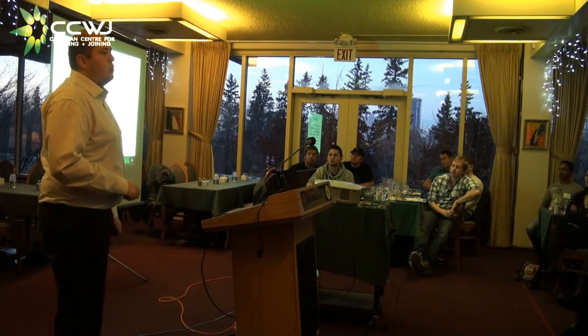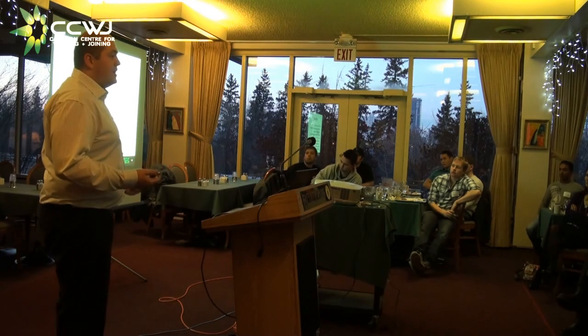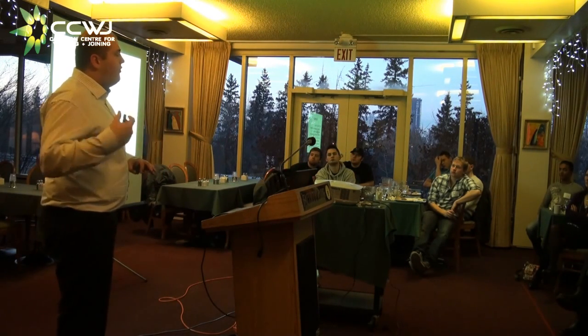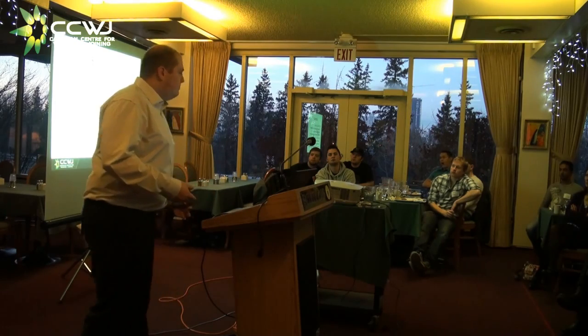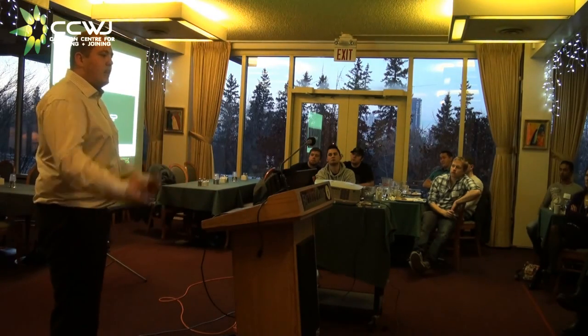We need to focus on arc stability through custom waveforms, modified short circuits, that kind of thing, to improve metal transfer. And then the hot wire process has the potential to take all those non-wetting and arc stability things and then feed in more carbide to it. So now we can start getting higher deposition rates and higher quality. So with that, any questions?